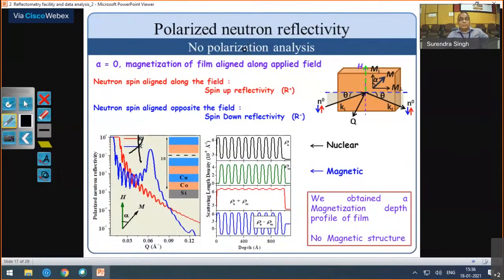This is used for getting the magnetization depth profile. Now see, this is the same one. When we don't have polarization, the typical reflectivity pattern is like this. So this I have already explained. We are getting the magnetization depth profile, not the magnetic structure. Meaning for cobalt, we will get the magnetization of each cobalt layer—10 bilayers are there—each cobalt bilayer, but all the magnetization in the cobalt layer are aligned along the applied field. I mean, what we say...